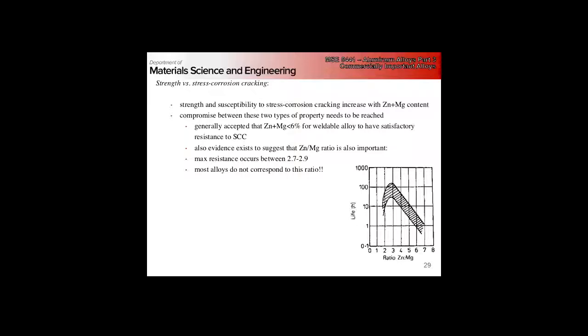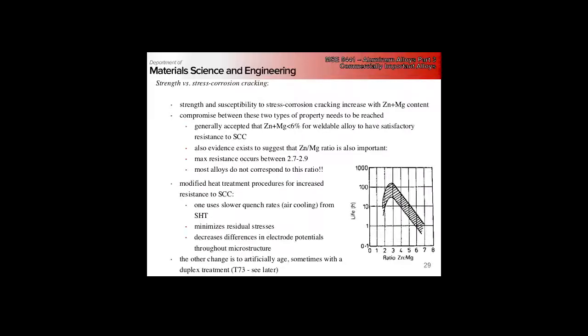Okay, sort of an academic point, there is an optimal magnesium to zinc ratio where you get the max stress corrosion resistance. It happens to be at about when you have almost 3 times as much zinc as magnesium, with the total zinc plus mag being less than 6%. But again, the interesting thing is when we look at the alloys that we actually use, none of them fall into this optimal ratio, for other reasons.